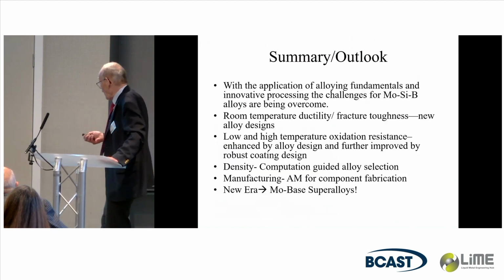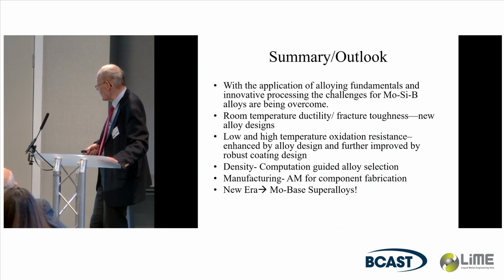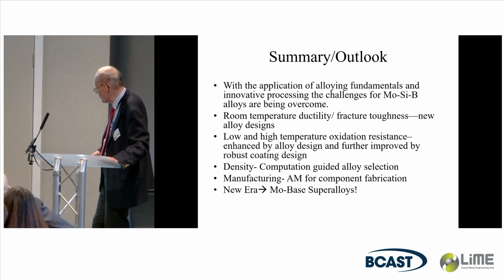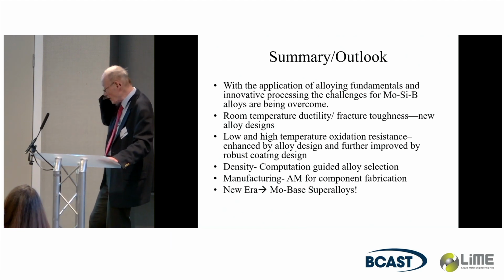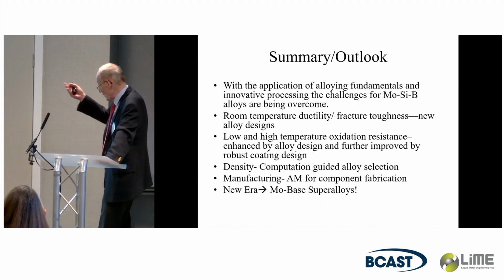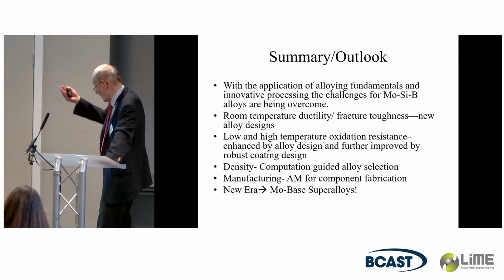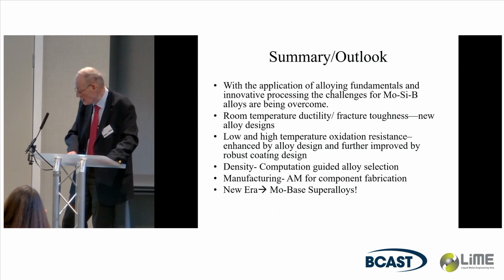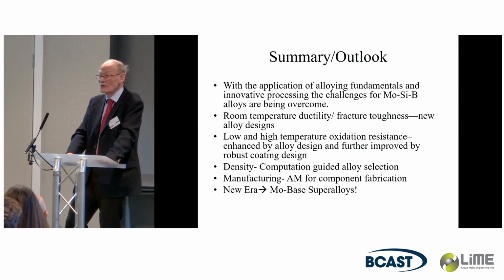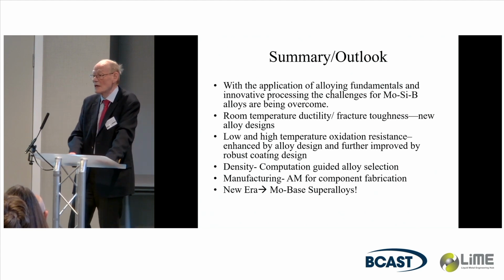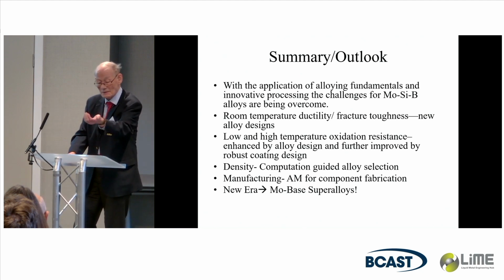So, again, with the application of alloying fundamentals and innovative processing, we've overcome all the challenges in the Mo-Si-B system: room temperature ductility, toughness, low temperature and high temperature oxidation resistance. I didn't talk about it, but we have a coating that takes care of that. Density guided by computational alloy analysis and manufacturing. So I think out of this program we'll get a refractory metal superalloy that'll replace the nickel and allow us to really improve the efficiency of these engines and power output. And thank you for your attention.